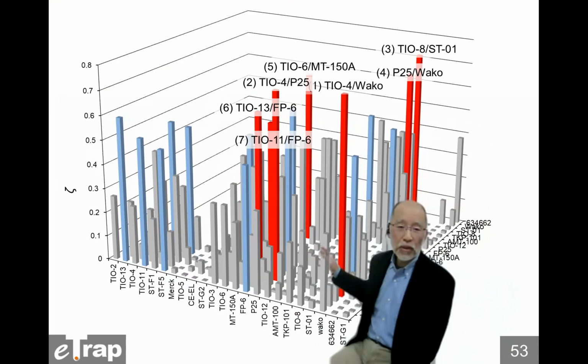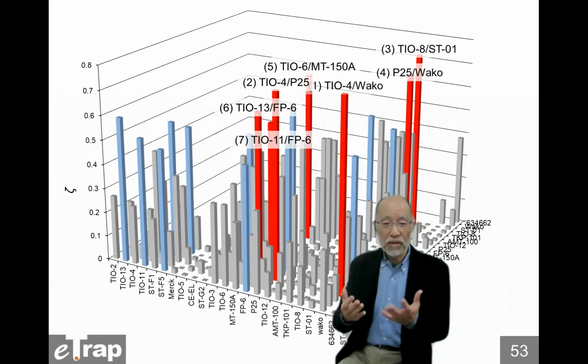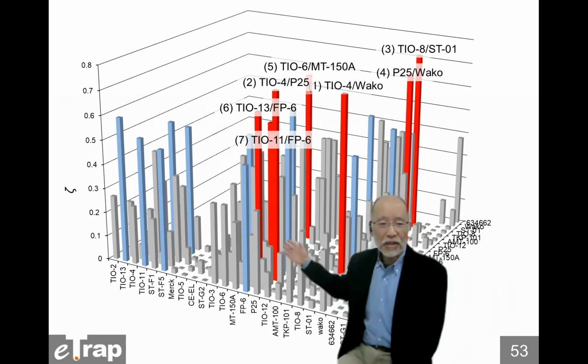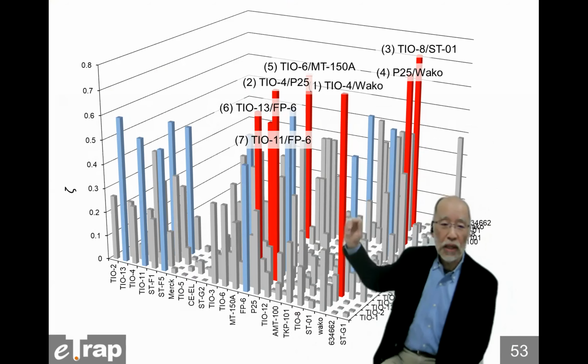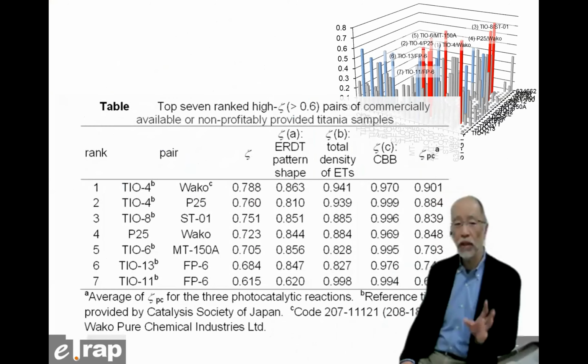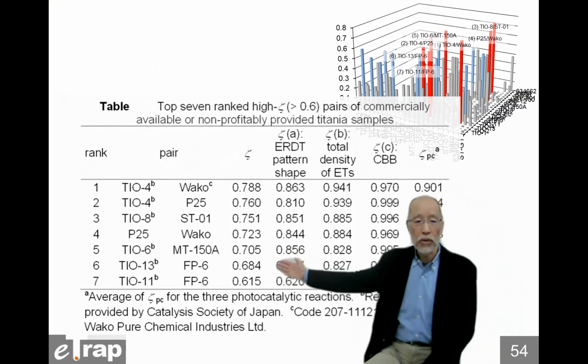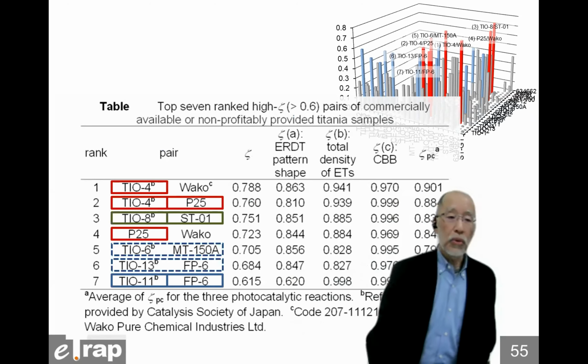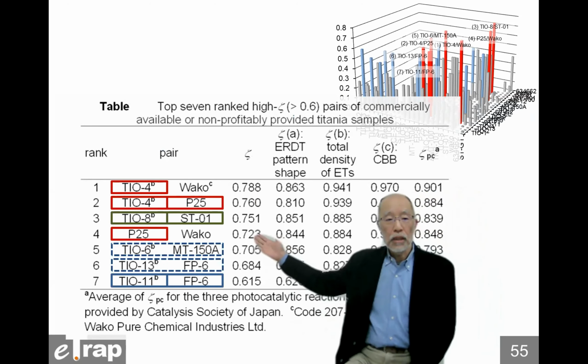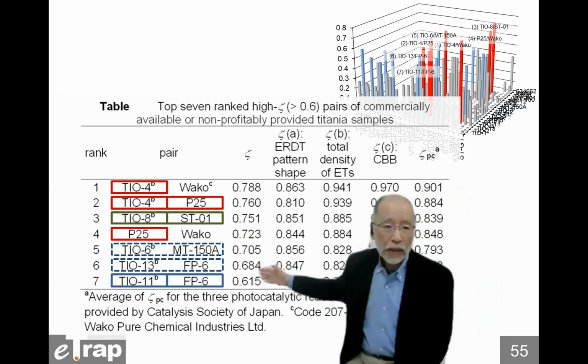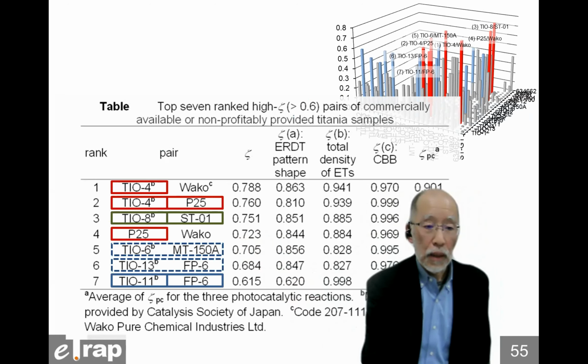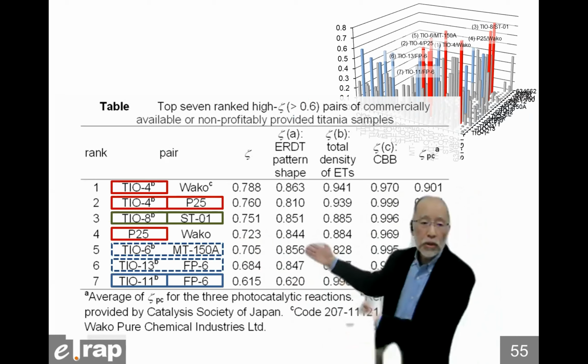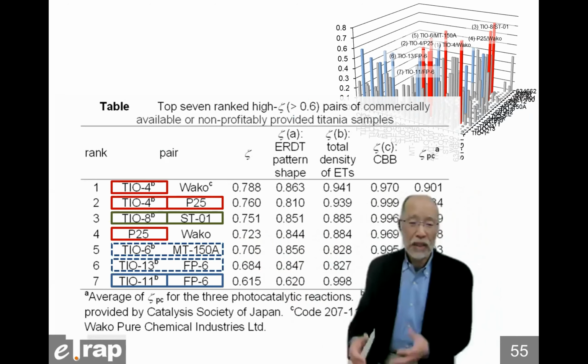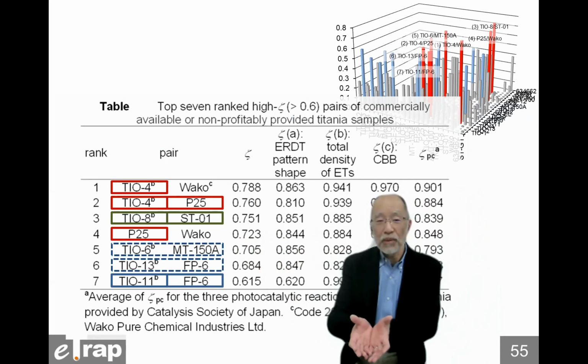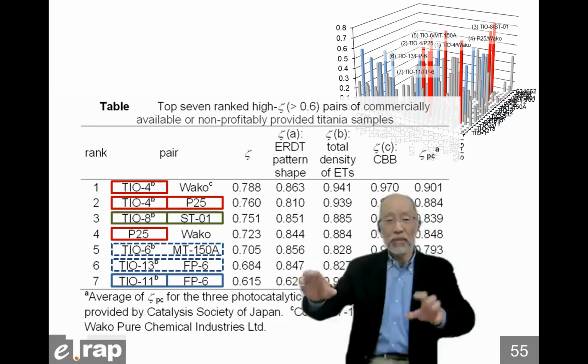Almost all the combination pairs show a very low zeta value. Of course, this is natural because they are different titanium oxides. But several pairs show a high degree of coincidence. This is the top 7 ranking of sample pairs with a higher degree of coincidence. Rank 2, TiO4 and P25, rank 3, TiO8 and ST01, and TiO11 with FP6 show a high degree of coincidence, but they are almost the same product supplied by the same company in a different way with a different code name. So this is natural.